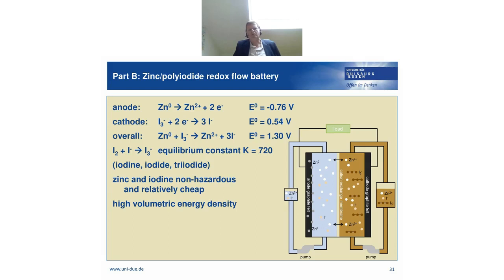And of course, we have zinc. Zinc on the anode side during discharge is oxidized, as it's well known, to give zinc ions. But on the cathode side, this time we have triiodide, negatively charged triiodide. This takes up the electrons to yield 3 ions of iodide. So the overall reaction is then depicted here. Zinc plus triiodide gives zinc ions and 3 ions of iodide. We have OCV, open circuit voltage, of around 1.3 volt.